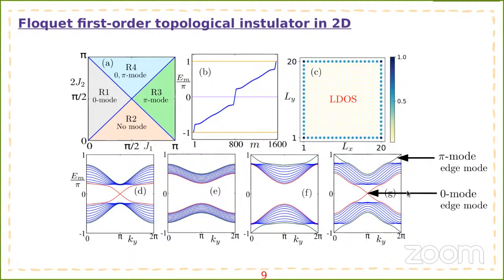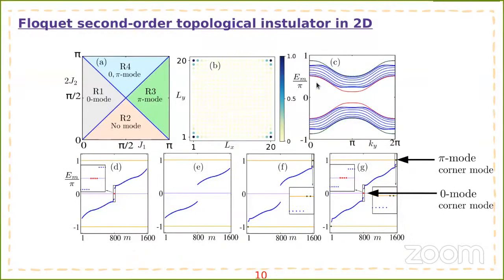So in region 4, to get the signature of the first order modes, we need to go into the ribbon geometry, and in ribbon geometry we diagonalize the Floquet operator and plot the energy spectrum, and you can see that there is a 0 mode close to the 0 energy, and there is also a pi mode close to the pi energy. And if we plot the local density of states, you can see that the modes are populated near the edges of the system.